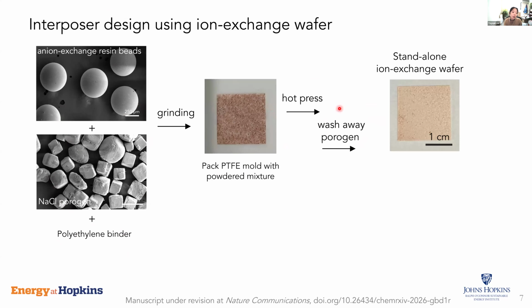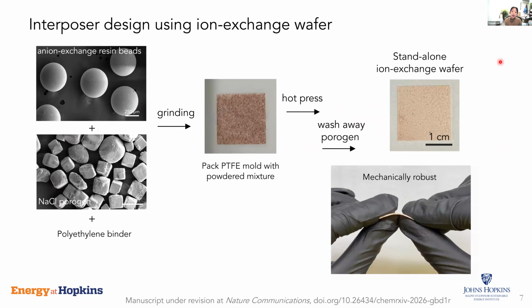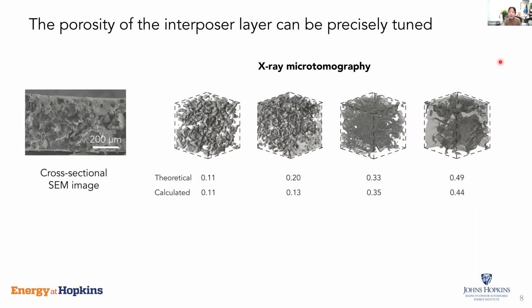And then we can put them in water and wash away the soluble sodium chloride porogen, and then we can get a standalone ion exchange wafer. And this resulting wafer is very mechanically robust. This is the student bending this wafer, showing the good mechanical stability.